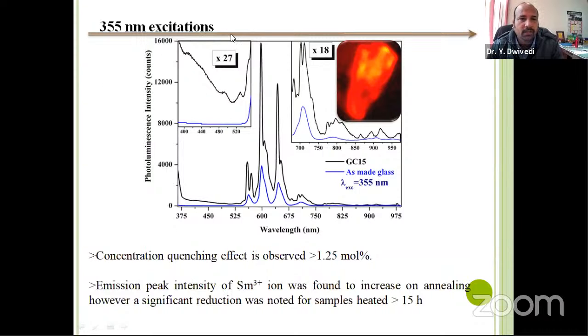So I want to share this photoluminescence spectrum of samarium doped glass ceramic and glass. Actually, we monitored this PL at 5-7 different excitation wavelengths, but I just want to share one so it can be visible. You see lots of transitions, but if you compare glass and glass ceramic, you can see the Stark splitting, and the intensity is very high in case of glass ceramic. This is direct evidence that microcrystallites are suitable to increase the emission intensity of samarium ion.